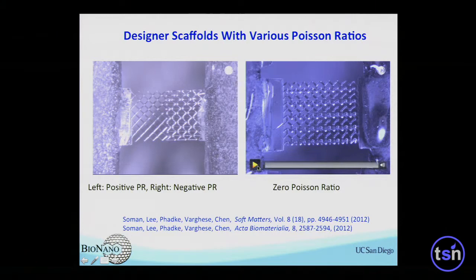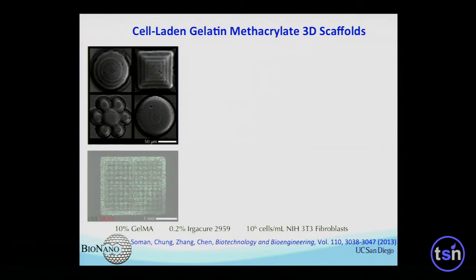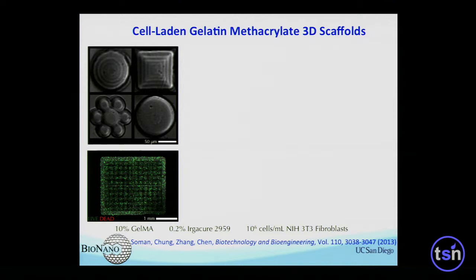You can get this because of the special geometries printed into the hydrogel. You can also create so-called zero Poisson's ratio material — when you stretch it, the dimension in the width direction doesn't change. The last thing I'd like to show is that we can encapsulate cells during the printing process. Because of free radical generation during polymerization, which is not cell-friendly, by adjusting photoinitiator types, concentration, UV polymerization time, we can manage cell survival rate to between 85% and 95% with cells inside.